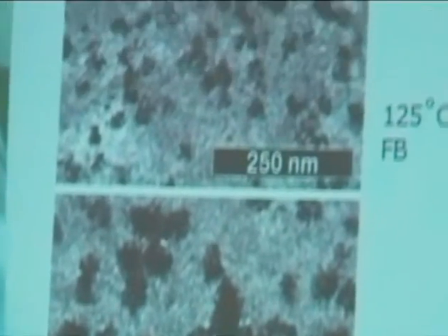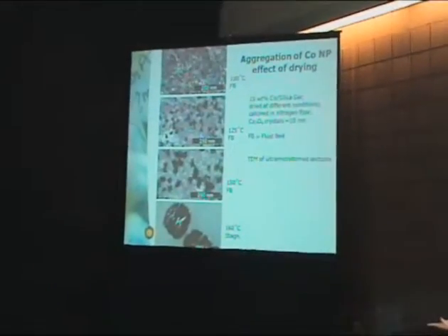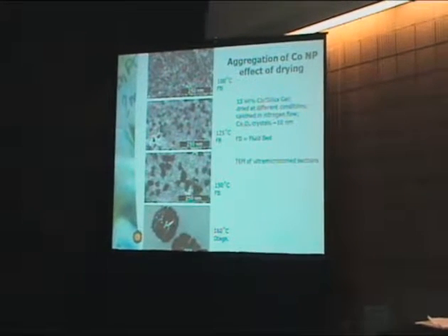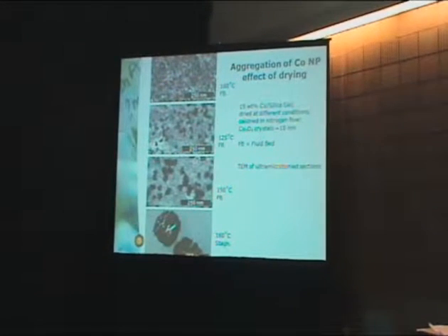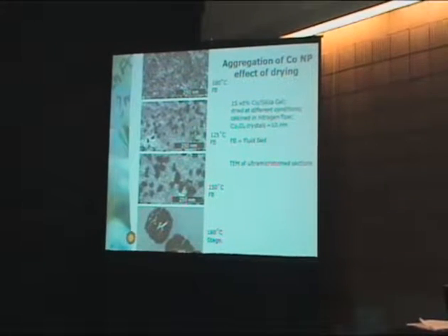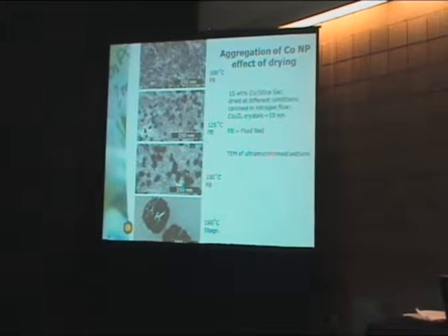But it is rather a distribution in aggregate size. So these are huge aggregates of about 200 nanometers. This is about 50 nanometers, 20 nanometers, and then in this case the aggregate size is close to the particle size. Sometimes we have a few particles together, but many of them are isolated. So we can control the aggregate size, and the question is, what is the impact on catalysis?